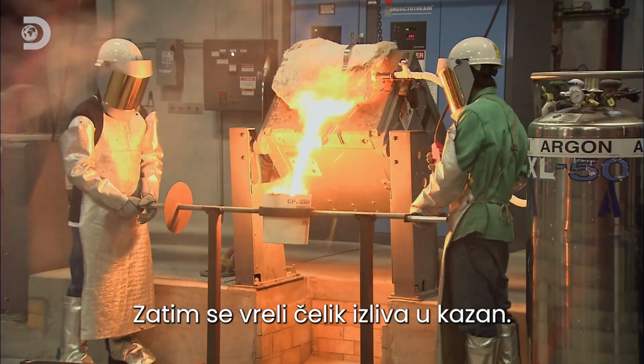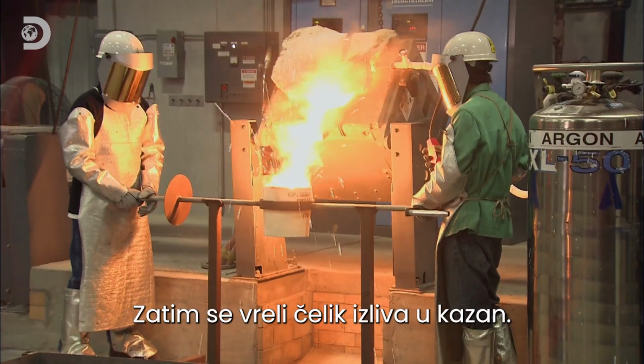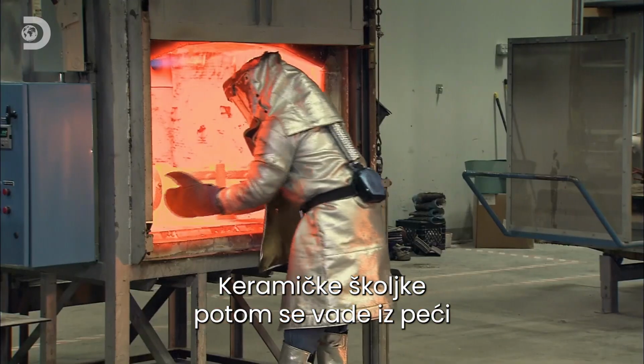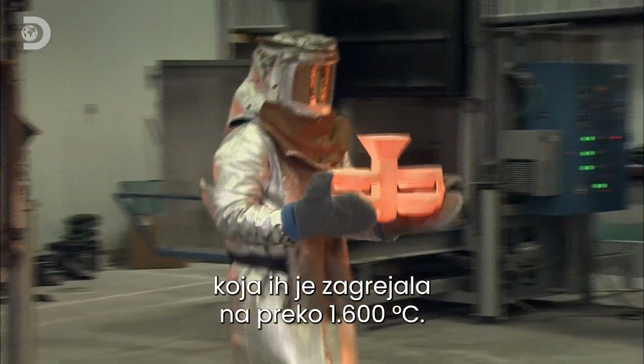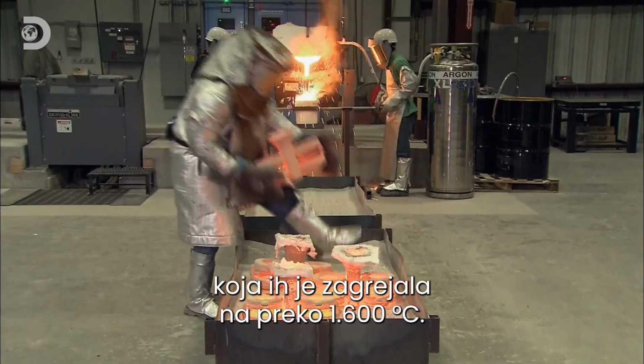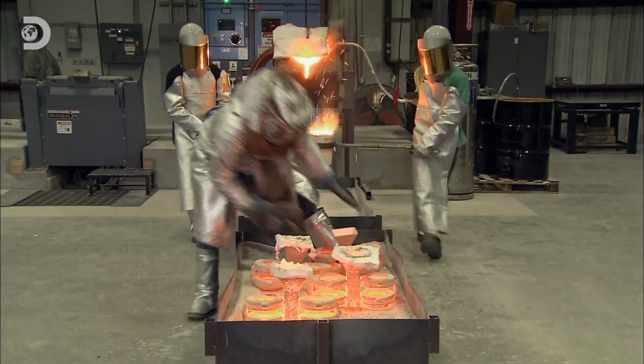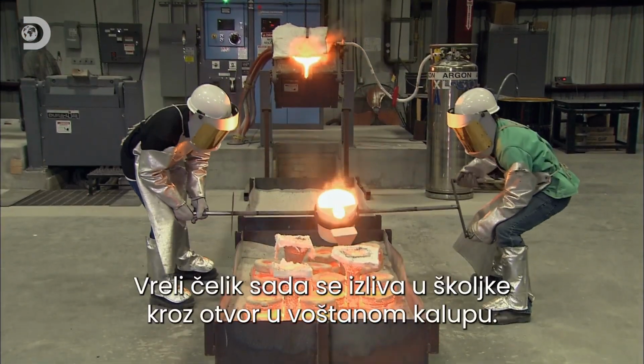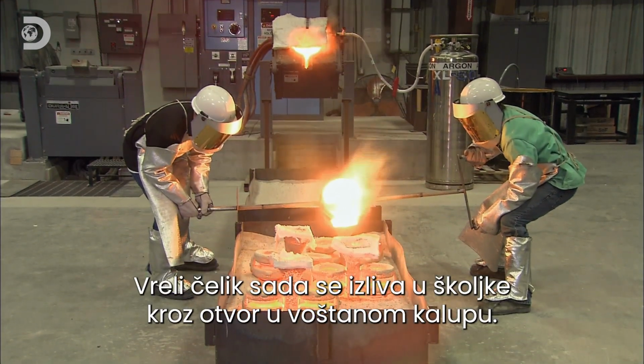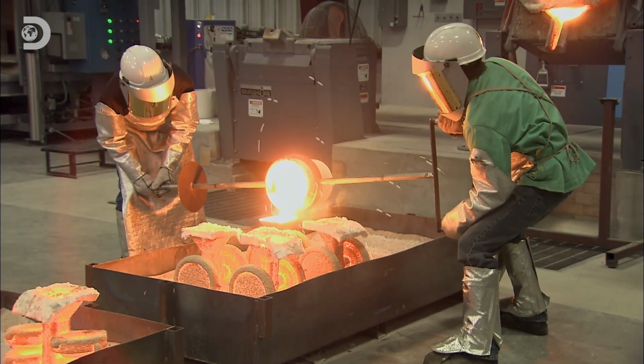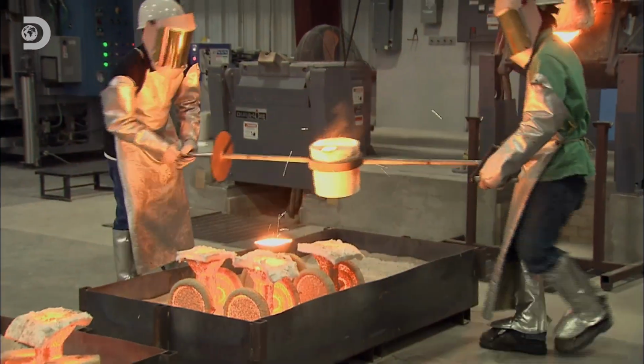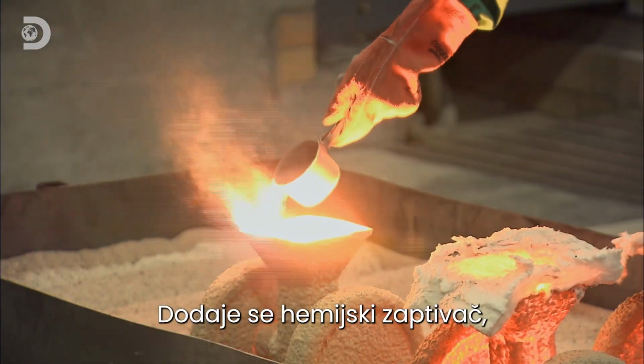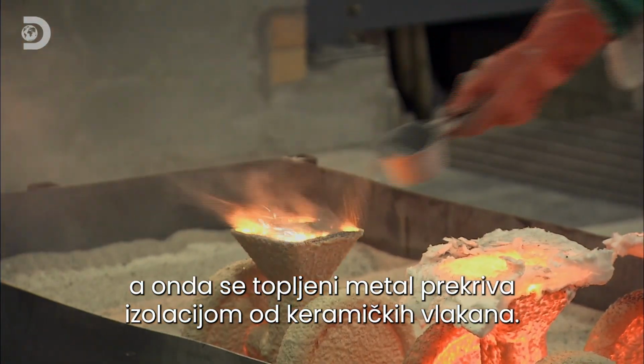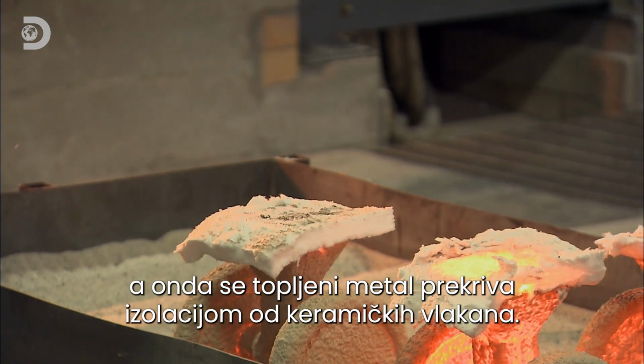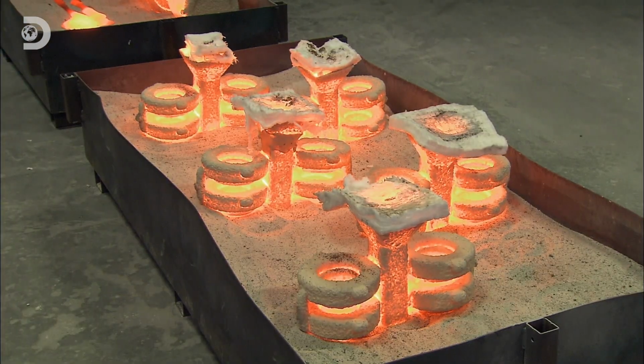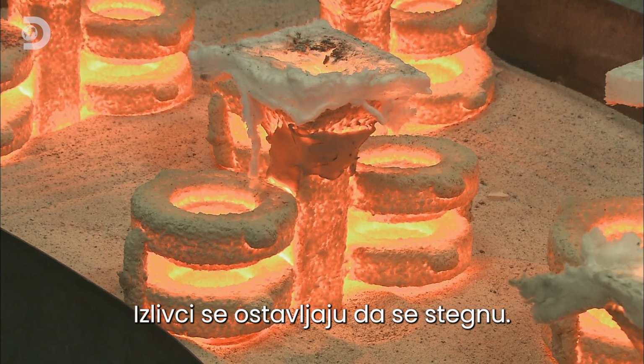Next, red-hot molten steel is poured into a ladle. The ceramic shells are then removed from the oven, which has heated them to more than 1,600 degrees Celsius. The hot steel is now poured into the shells through an opening in the wax tree. A chemical sealer is added before the molten metal is topped with a piece of ceramic fiber insulation. The castings are then left to cure.